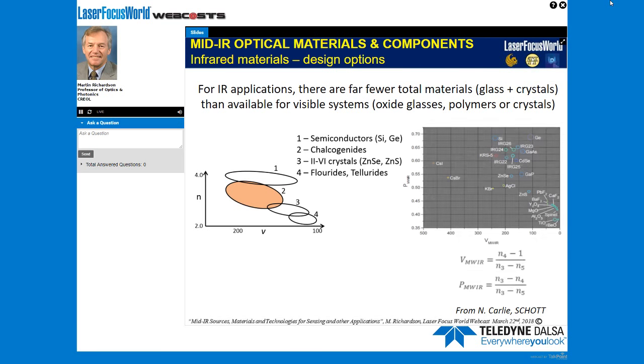So you see in this region here, if we look at the curve of refractive index against the Abbe number, for instance, that's in both these diagrams here, one plotted against the Abbe number. So basically looking at refractive index as a function of dispersion. Then there are various regions where the semiconductors work well, but with high refractive indexes. There are disadvantages there. The fluorides and tellurides really only operate in very highly dispersive regions, and the II-VI crystals also have high dispersion.